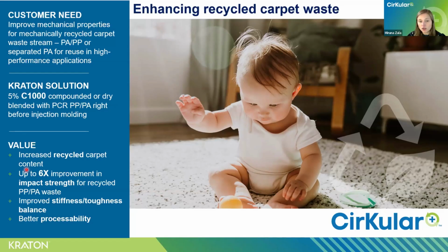First, using C1000 allowed them to significantly boost the amount of recycled carpet material they could use, meeting their sustainability goals. But beyond that, the mechanical properties considerably improved. And here we are not talking low numbers, we are talking about up to 6 times increase in impact strength, along with a much better balance between stiffness and toughness.